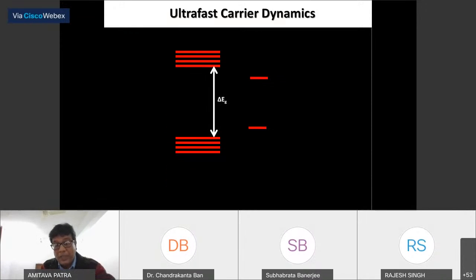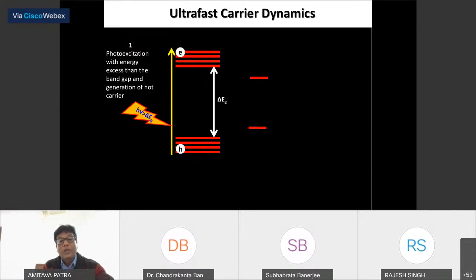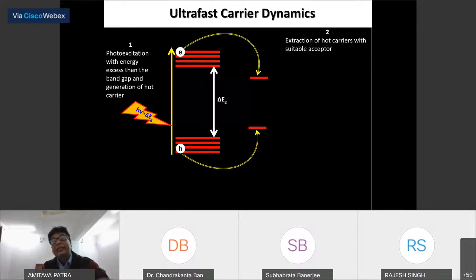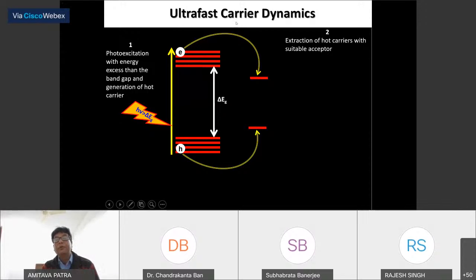So recently we have tried to understand the hot electron extraction process by ultrafast kinetics, that is femtosecond time scale, that is 10 to the power minus 15 seconds. So I'll show you. This is the valence band and conduction band. If you excite in this band gap, then there is no problem. Or if you excite higher than the band gap, the electron goes from here to here, then what happens? This is the hot electron. This electron you can extract by a suitable acceptor or anything. This kinetics takes place in less than 1 picosecond.